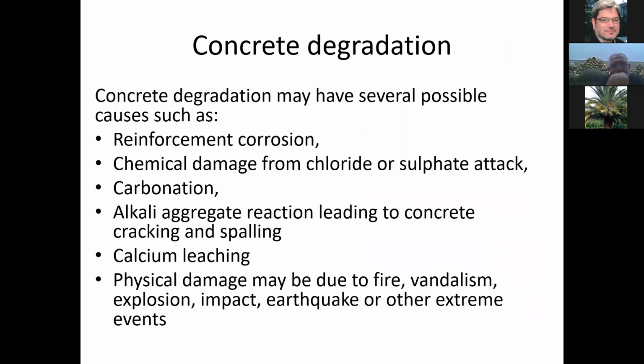As you know, in addition to the increases in traffic volumes and mass, concrete degrades with time. So concrete degradation is very important to consider when we strengthen structures. You get reinforcement corrosion, chemical damage from chloride or sulfate attack, carbonation of concrete, alkali aggregate reaction leading to concrete cracking and spalling, calcium leaching, and physical damage due to fire, vandalism, explosion, and so on. So there are many causes of damage to concrete that we can see during the service life.